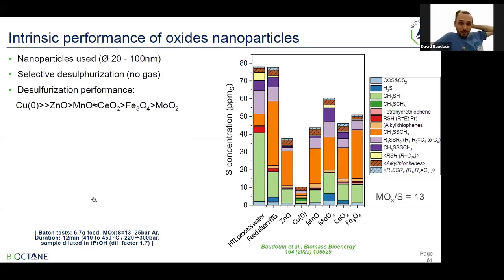So I'm now moving back to the sulfur case, sulfur trap, sulfur desulfurization materials. In this graph on the right are represented the sulfur concentration and the class of compounds found after treating the stream entering the sulfur trap bed, and the effect of different materials on these organosulfur compounds present in the inlet. And you can clearly see that copper was identified as a very good material for removing the volatile organosulfur compounds present in the stream.